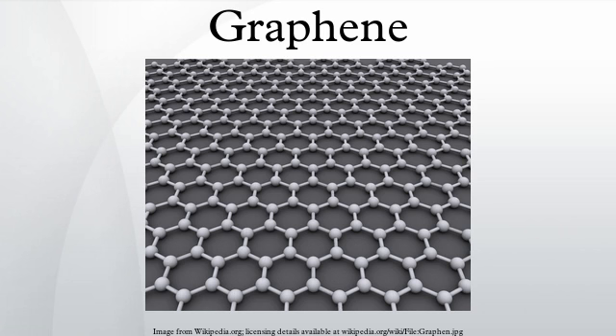Fiber. In 2011, Xinming Li and Hongwei Zhu from Tsinghua University reported a novel yet simple approach to fabricate graphene fibers from chemical vapor deposition grown graphene films. The method was scalable and controllable, delivering tunable morphology and pore structure by controlling the evaporation of solvents with suitable surface tension. Flexible all-solid-state supercapacitors based on these graphene fibers were demonstrated in 2013.